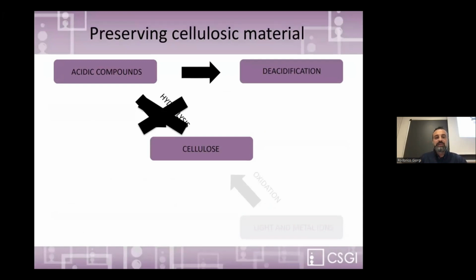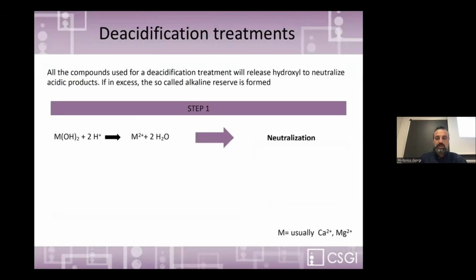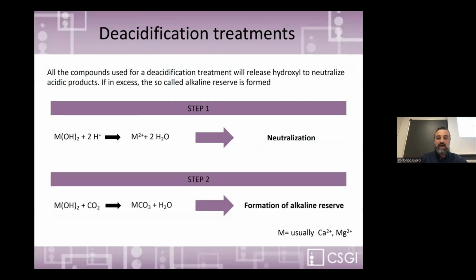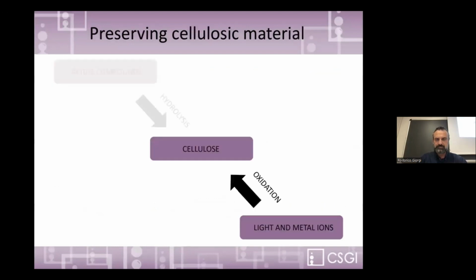So it is pretty well known that hydrolysis can be inhibited by the application of alkaline materials to get a complete de-acidification. And this means neutralization reaction, basically based on hydroxide application. And the second, fundamental step is the formation of an alkaline reserve. We are pretty used to consider the two processes, hydrolysis and oxidation, as a little disconnected and both very important to degrade paper, and for that we need to have methods to inhibit the two processes.